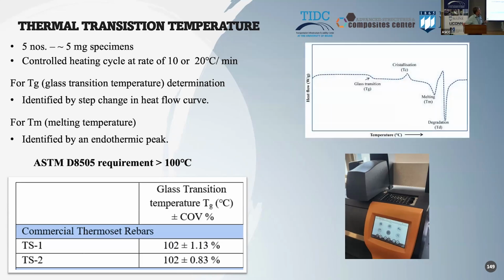Next one. The chart that I showed before can be obtained using a test called dynamic mechanical analysis. There is another way to measure the glass transition temperature through differential scanning calorimetry, where what we do is we measure the heat flow and we look at the peaks, exotherm and endotherm. They're shown there for the glass transition. There's a little bump when crystallization temperature happens, the melting temperature, as well as the degradation of that polymer. There are, again, two test methods that are within the standard. Each one gives us a different perspective on how the material changes with temperature.